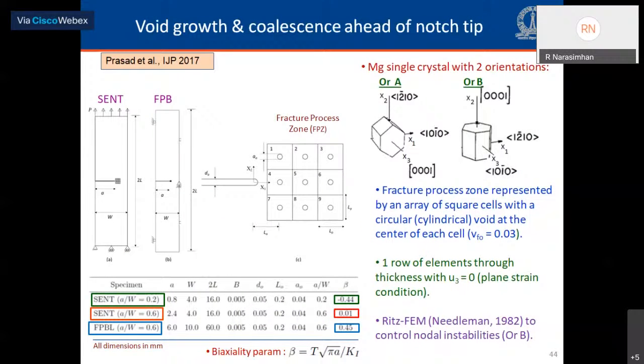Now, the last two slides in my presentation are going to be on some results from our specimen analysis using magnesium single crystals. And we analyzed two different geometries, single edge notch subjected to tension and 4-point bend. Again, two orientations, orientation A where the C-axis is along the thickness direction, and orientation B where the C-axis is along the normal to the flat surface of the notch.